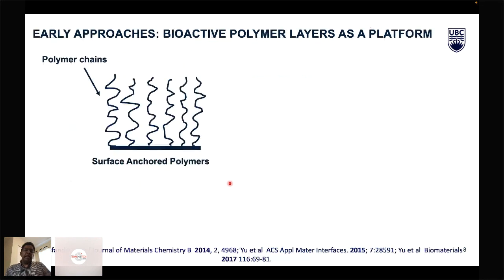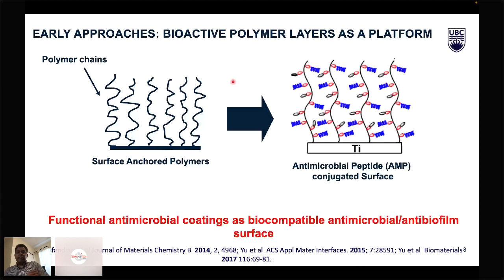So in our early work, started in 2009, 2010, we were working on polymer layers or polymer surface coatings, which are called polymer brushes, and surface anchored polymers. And we thought, can we adapt these coatings to develop antimicrobial surfaces? Our goal is to use a functionalized polymer layer to attach antimicrobial peptides or antimicrobial agents on the surface, and to generate a surface which is antimicrobial as well as anti-adhesive.